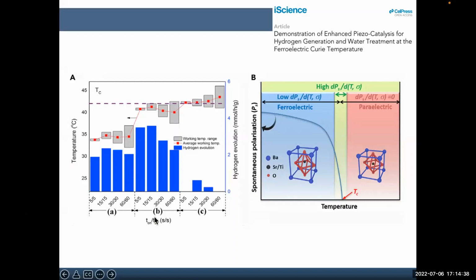And that's exactly what we saw when we changed the conditions of the experiments. We got better hydrogen generation when we operated near the Curie temperature. And obviously when we exceeded the Curie temperature, then the reaction rate, or the hydrogen generation, went down. And again, that gives us a good feeling that there's clearly some ferroelectric contribution to what's going on within the reaction.